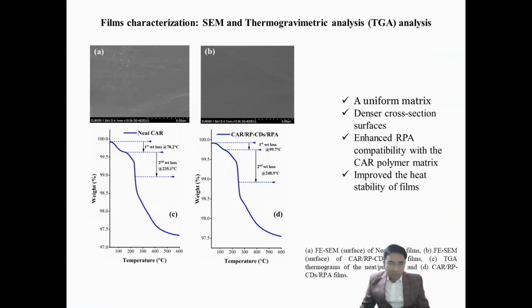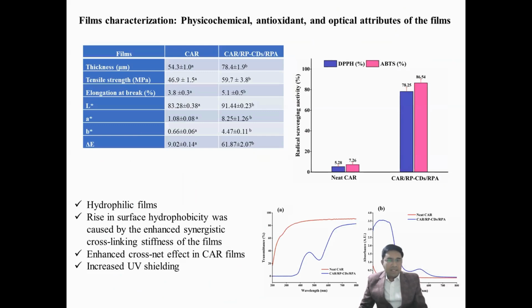Then coming to the next, the SEM analysis, the scanning electron microscopy, and the thermogravimetric analysis. We have done that, and here we found that the carrageenan films, when they are added with these carbon dots as well as with these anthocyanins, perform in a good manner. They have a uniform matrix, denser cross-sectional surfaces, and uniformity. These added ingredients are distributed uniformly in the film. Again, in the TG analysis, we found there is an improvement in the stability of the film. So here we can conclude that the carrageenan, when added with these active as well as intelligent ingredients, is doing its best in terms of SEM as well as in terms of thermogravimetric analysis.